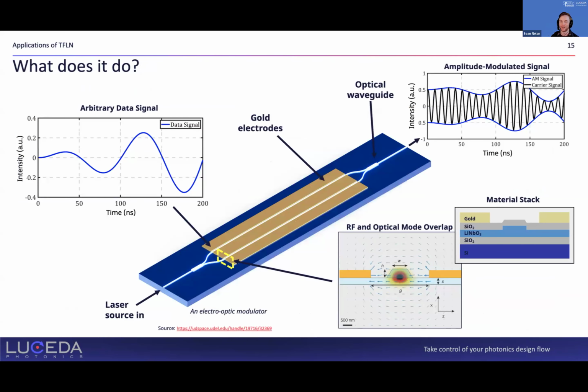And when I talk about a modulator, why is it so important? Here I've highlighted some of the core characteristics of a modulator. First, I'd like to highlight the fact that a modulator converts an arbitrary electrical data signal and overlays that onto, in this case, an amplitude modulated optical signal. More on this in a bit, but the way that it does this is when we have our optical field highlighted in the center here, going through our waveguide between our metal electrodes, in some cases gold, copper, aluminum.